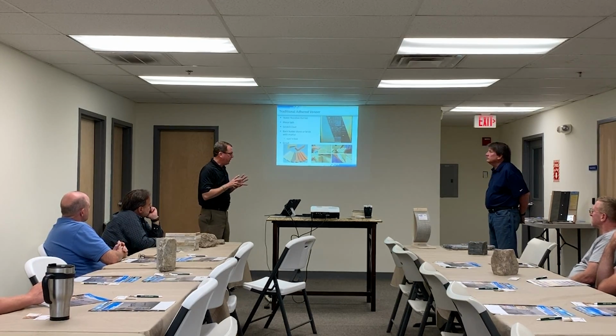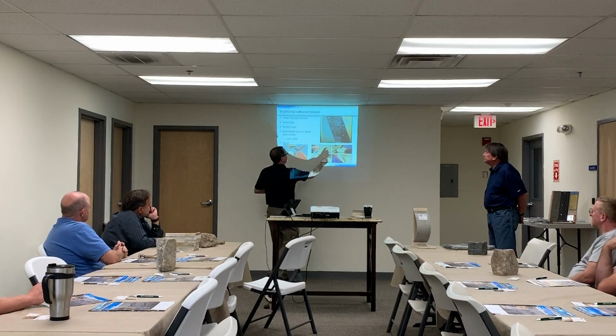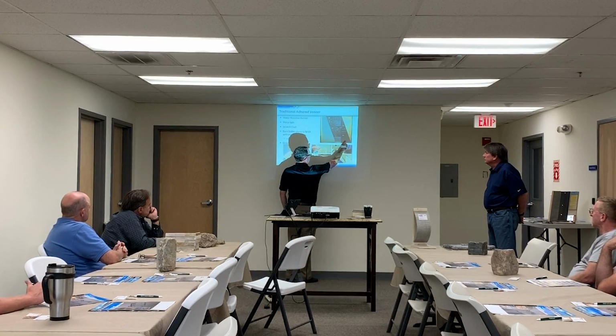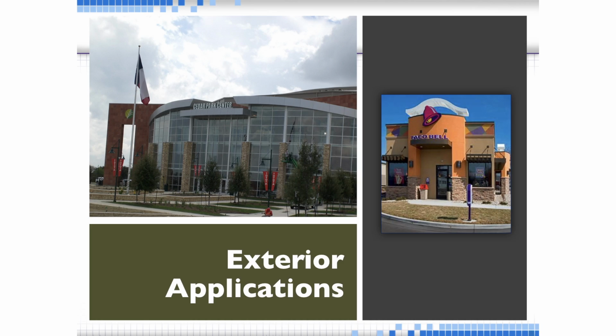So what we're proposing is to get rid of, you need a weather barrier, but we're not going to use this weather barrier, and we're going to get rid of all of this. And the cement board now becomes the lath and scratch coat. It replaces the fact that you've got to mix it up on a job site. You can't work if it's 25 degrees, and in this neck of the woods, it's 25 degrees a lot more than it is where I live in Philly, right? So you've got temperature issues. You won't have that with this.